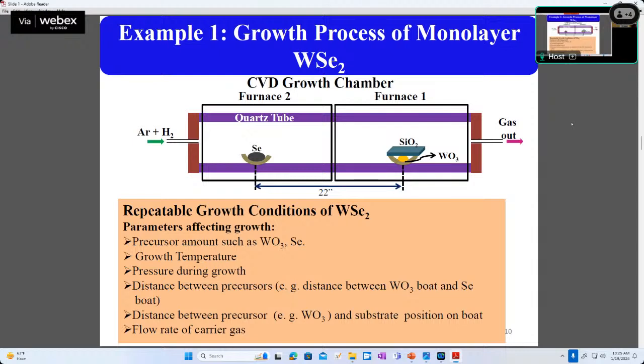So to achieve the desired properties, there are various parameters which can be varied, like precursor amount, how much selenium and WO3 you are keeping, that will decide the quality of the grown WSe2 material. And the growth temperature, pressure during growth, distance between precursors, substrate position on the boat, flow rate of carrier gases. So all these are the parameters which you have flexibility to tune to achieve your desired properties for any desired application. Okay. So in a similar way, one can do growth of any sulfide or selenide material.